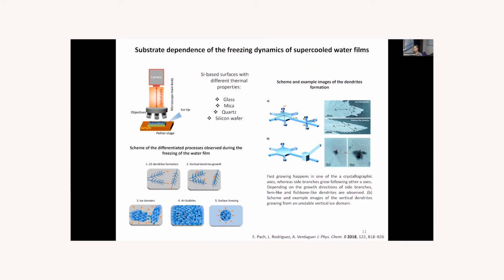But we could separate these two processes into five different steps, which can be studied separately. This is the two-dimensional dendritic formation, then vertical dendritic growth into the bulk of the water, ice domains formation and expansion, trapping of the air bubbles, and finally the surface freezing. We could see the formation of different dendrites, the fern-like dendrites with the A-axis like this, and the fishbone-like dendrites, which are formed in a different way.